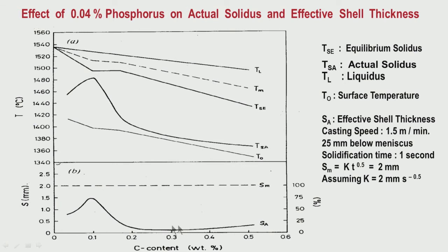As such, it increases with normal carbon, as you can find from the iron carbon equilibrium diagram, but due to the presence of other alloying elements, due to microsegregation, all alloying elements will cause suppression of the actual solidus. The actual solidus will be lower compared to the equilibrium solidus, but the carbon concentration, the mode of solidification, will tell us quantitatively what that extent is.